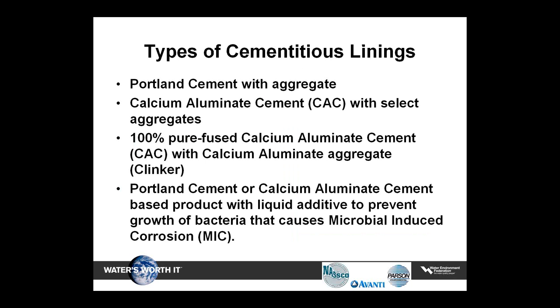Common types of these products include Portland cement with aggregate, which is typically a fine-grained sand; calcium aluminate cement with select aggregate; calcium aluminate cement with calcium aluminate aggregate, which is referred to as clinker, and it is a byproduct from the processing of the calcium aluminate cement; and also Portland or calcium aluminate cement-based products with a liquid additive to prevent growth of bacteria that causes microbial-induced corrosion, or MIC.